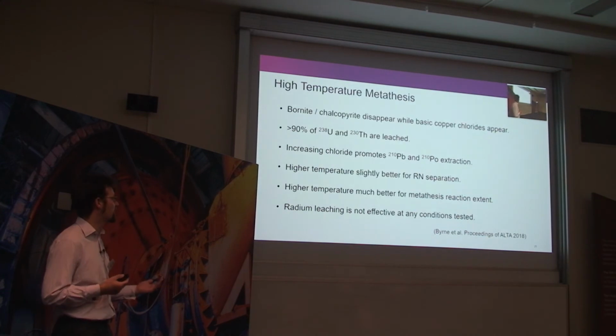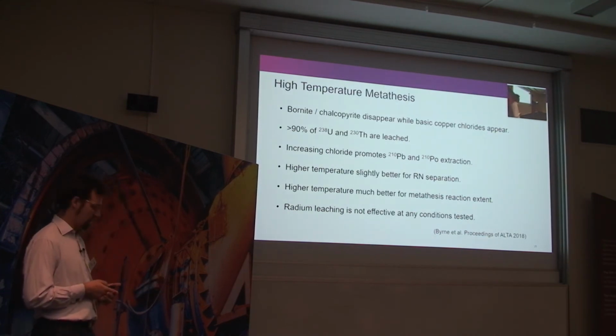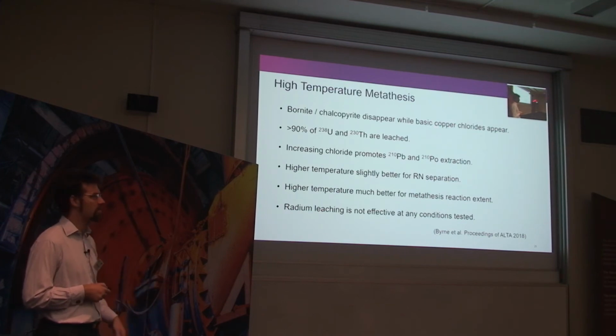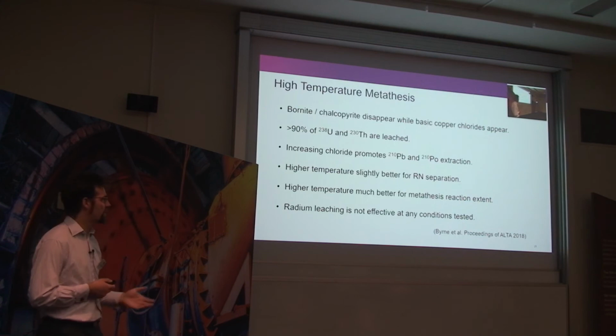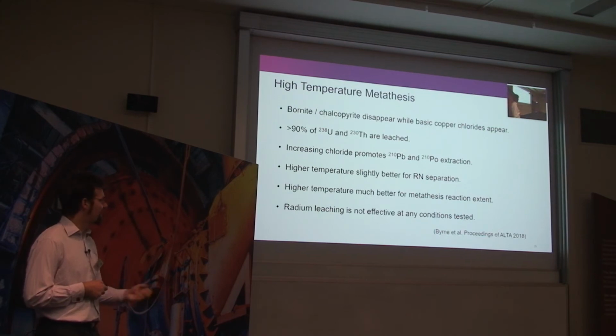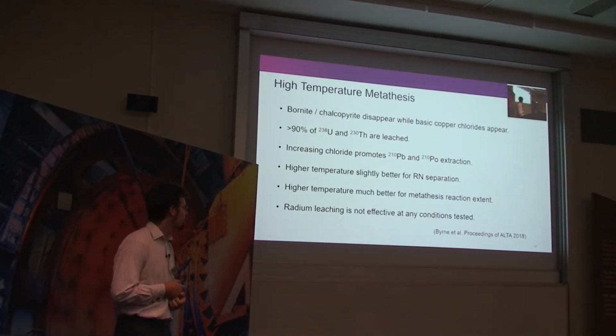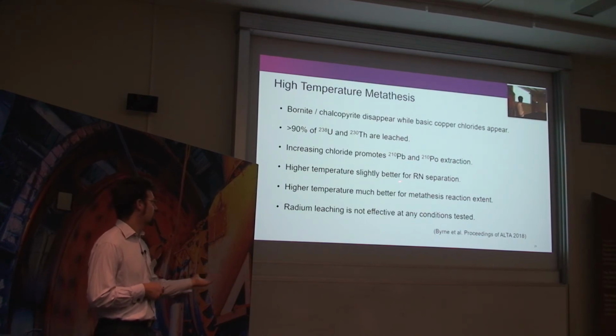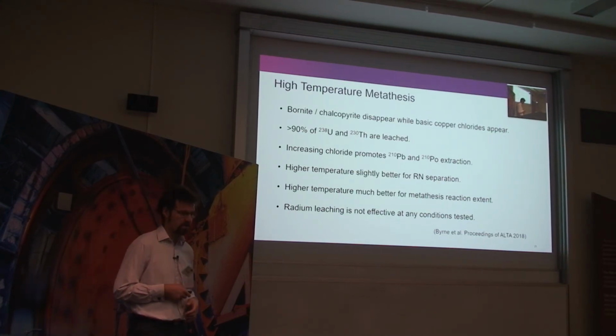Okay, so a bit of a summary about high temperature metathesis from our studies. I didn't show these results, but bornite and chalcopyrite disappear and basic copper chlorides appear in the study, so we did have some chloride in our final residues. Greater than 90% of the uranium and thorium are separated quite easily at almost all conditions. Increasing chlorides promotes lead and polonium extraction, and the higher temperature is slightly better for radon (Rn) separation. Higher temperature is much better for the metathesis reaction extent overall, and radium was not leached effectively in any of the conditions tested.